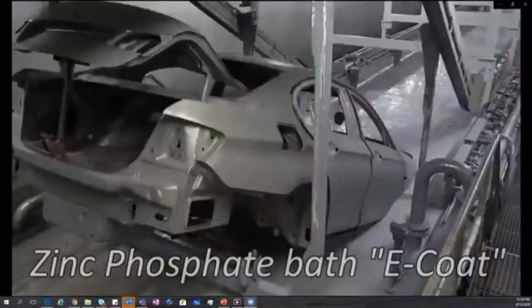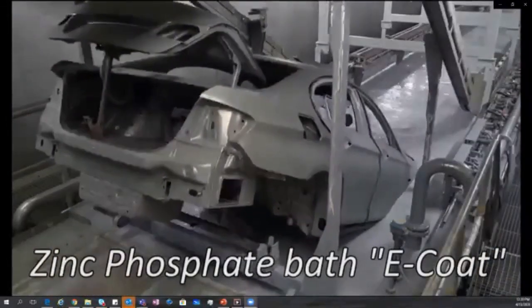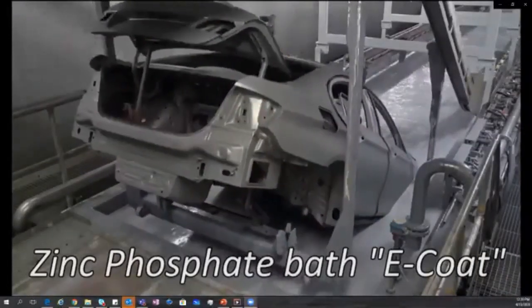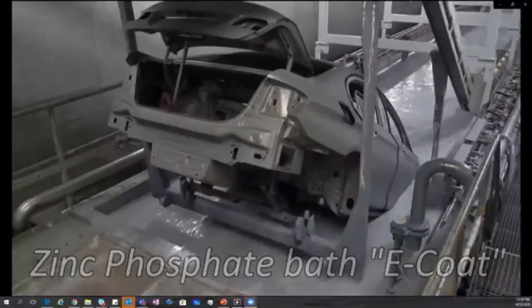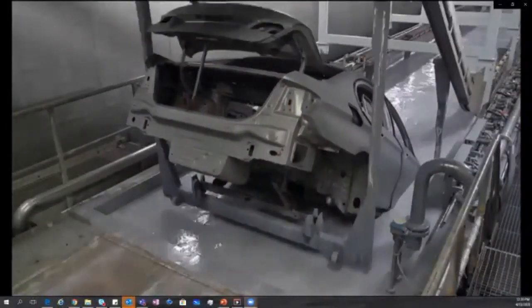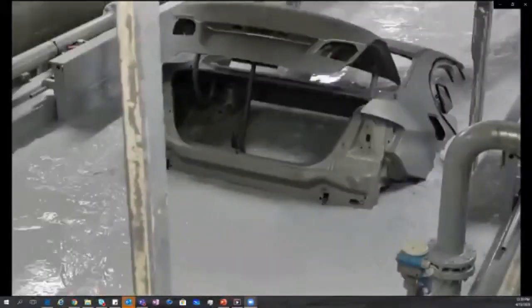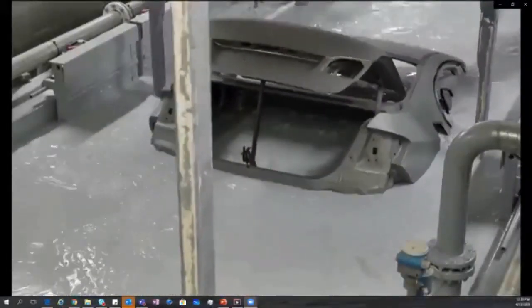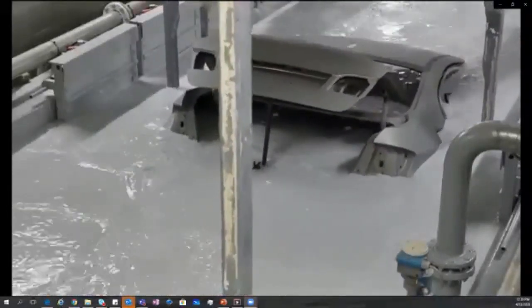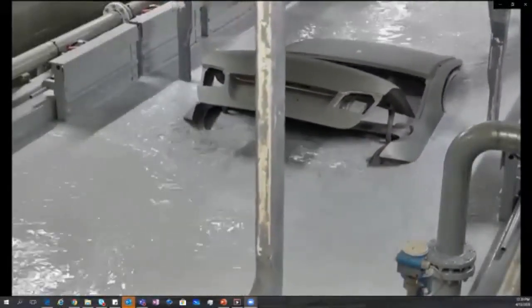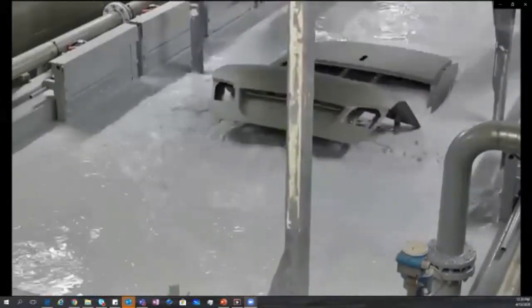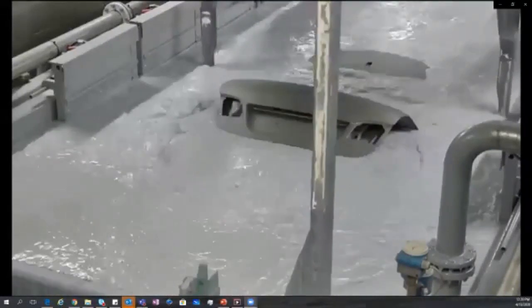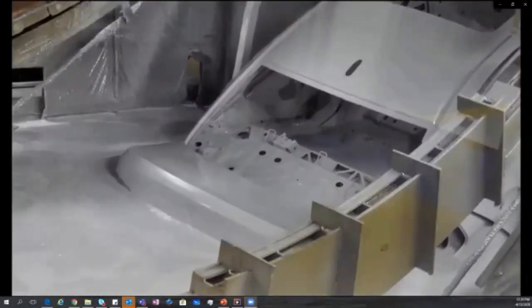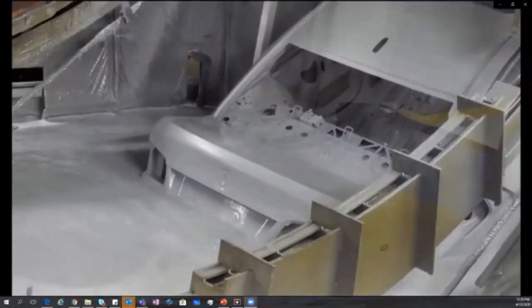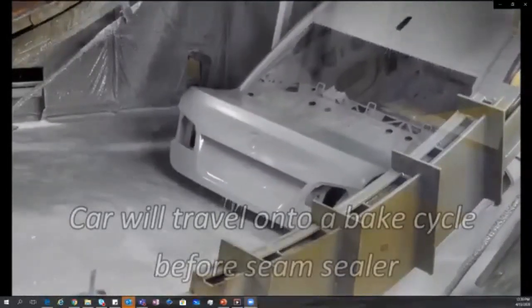and this e-coat process. So as you see here, this vehicle is being fully submerged in a bath. And in all of these bath cycles, the bath itself is positively charged, and the vehicle itself is negatively charged. And this way we get good surface conductivity of the materials, right? These materials are getting a good true bond to the surface this way. They're also, because it's such a liquid state, getting in between all these weld zones, right? So these cars are welded together, they're bolted together, and then the e-coat is actually being allowed to work its way in between and protect all the bare metal surfaces through this process.